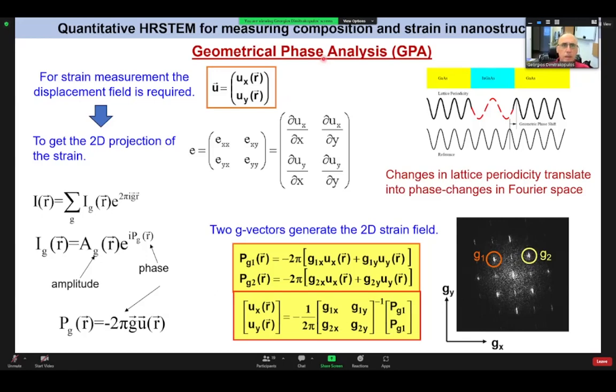For example, if you have a material that changes its structure, like here you have gallium arsenide, and then you have indium gallium arsenide, and then back to gallium arsenide, the lattice periodicity is going to change. So when you want to identify this change in the lattice periodicity, you identify it through the displacement field in this particular region of the indium gallium arsenide. And from this, of course, you can get then the strain field by differentiating, taking the first derivative of the displacement field.